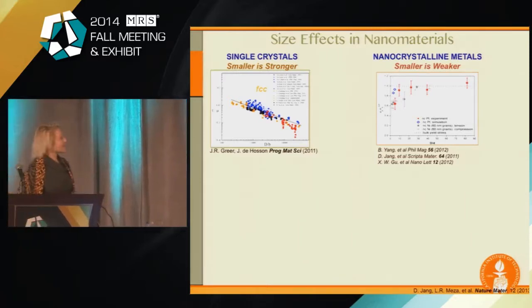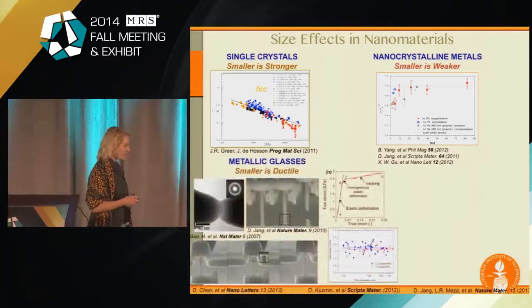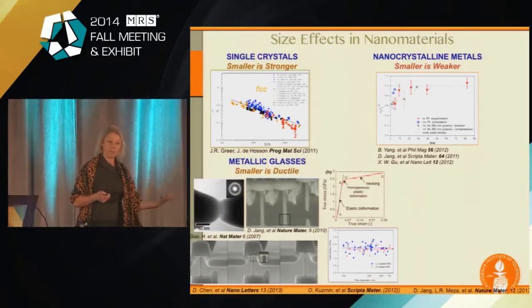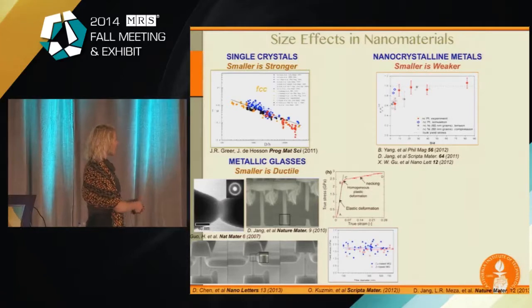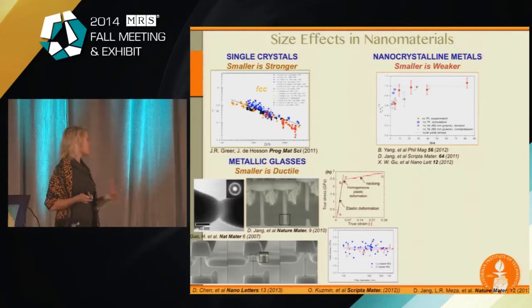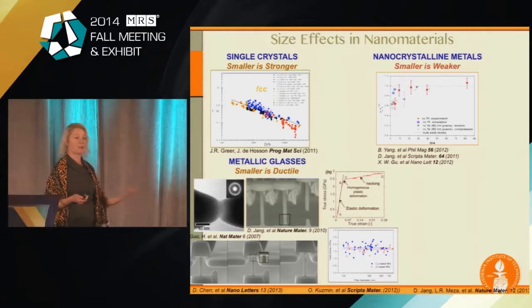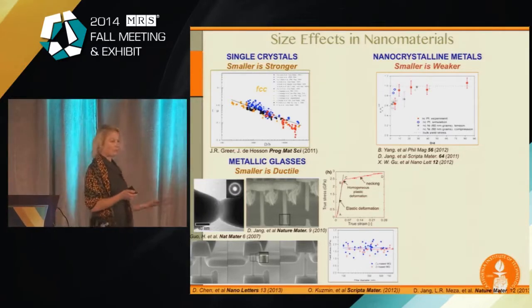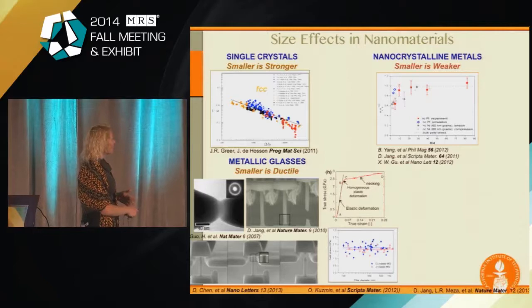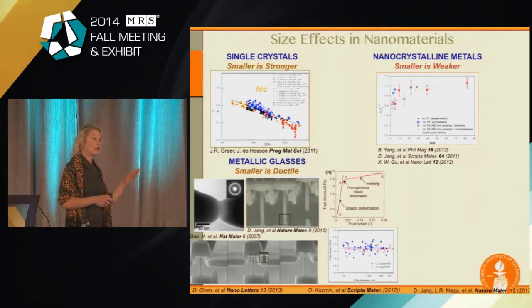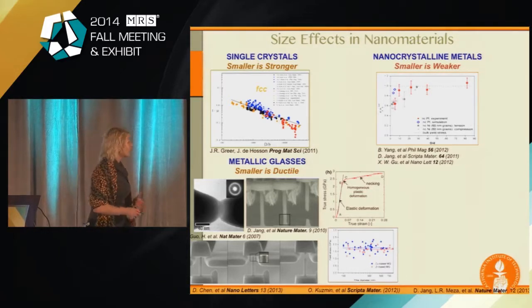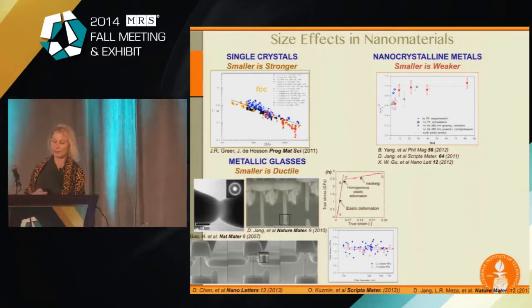But actually, the size effect doesn't manifest itself only in strength. Sometimes it manifests itself in transitioning a material from being intrinsically brittle to being ductile. For example, metallic glasses, a type of glass which is made out entirely of metals, but it's a glass, and we all know what happens when a glass falls down on the floor, it shatters. What we were able to show is that at a small enough size, these glasses become ductile without any sacrifice in strength. So this is the strength as a function of size. It looks like we're not losing the strength. They still remain strong, but we're now able to deform them a lot more than we would ever be able to do in a large material.